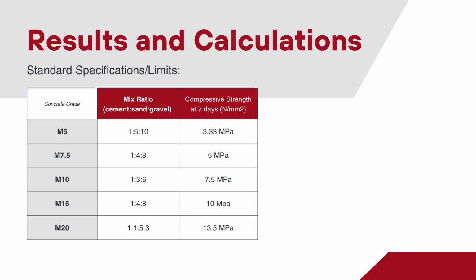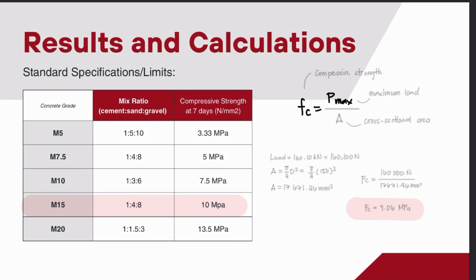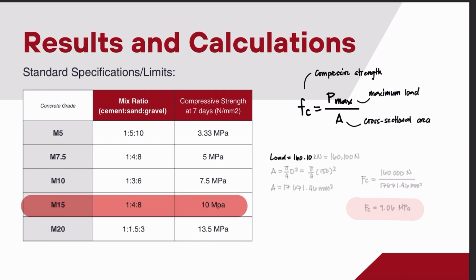Results and discussion. Use fc = Pmax / A to calculate the compressive strength of the cylinder, where Pmax is the maximum load it can carry, and A is the cross-sectional area of the cylinder. The diameter of the cylinder is measured to be 150 millimeters, which gives us the compressive strength of 9.06 megapascals, meaning this concrete cylinder failed to meet the standard compressive strength for an M15 concrete grade.